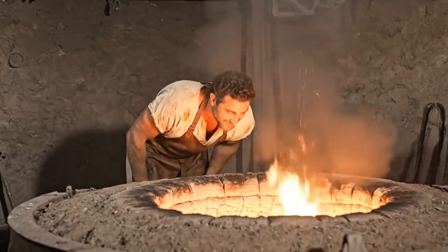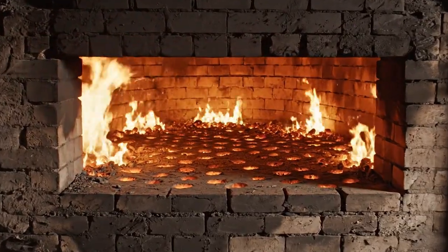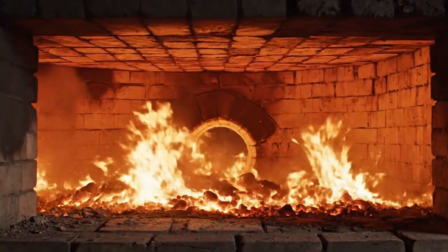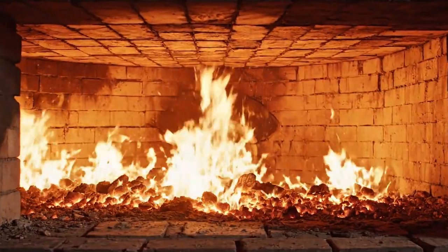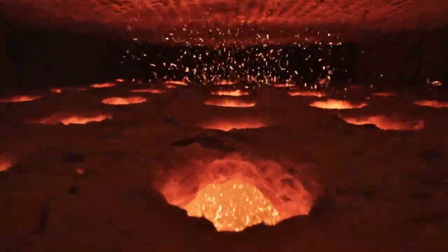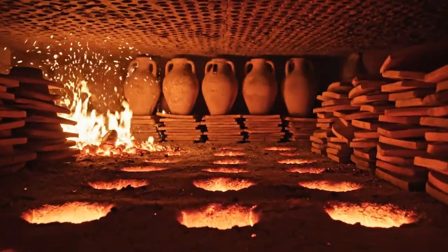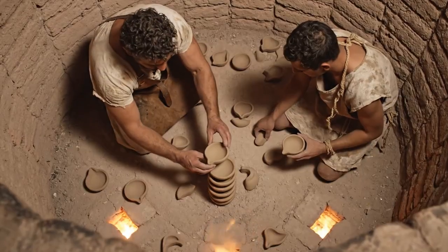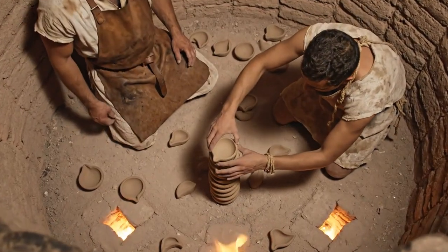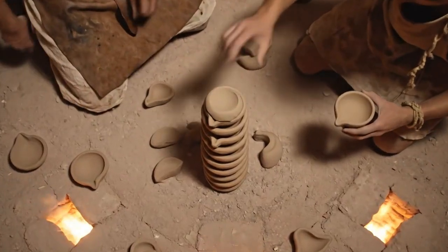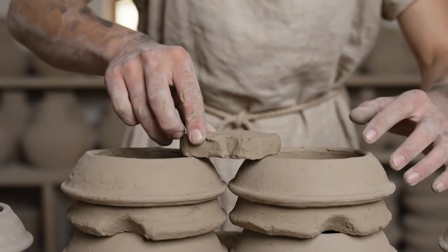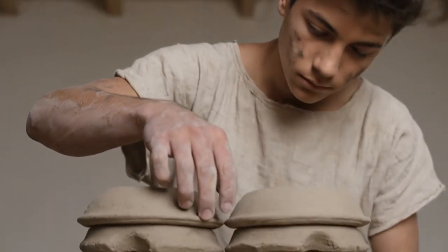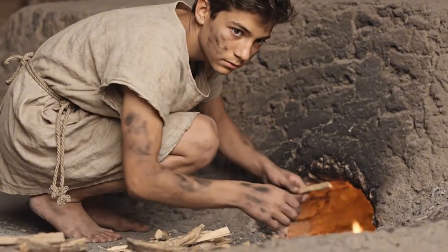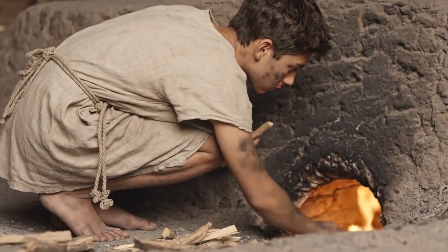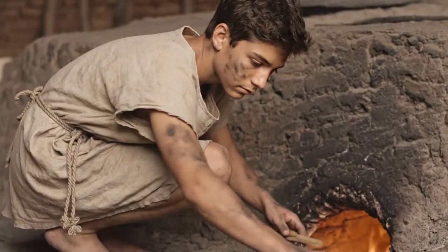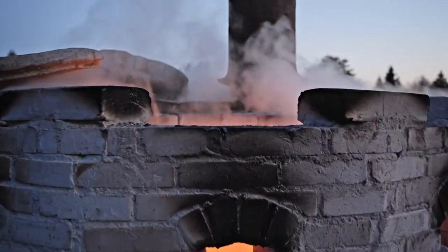And so we return to the kiln, that furnace we opened with, its belly now aglow. Roman pottery kilns of this era are typically 2-chambered updraft designs, a lower combustion chamber, or praefurnium, where fuel is burned, separated from an upper firing chamber by a perforated clay floor that allows heat to rise evenly through dozens of small vents. The lamps are carefully stacked in the upper chamber, often separated by small clay spacers called kiln furniture, which prevent them from fusing together during the melt. The stoker begins with a low fire, gradually increasing the temperature over many hours to drive off the last molecular traces of water without thermal shock.